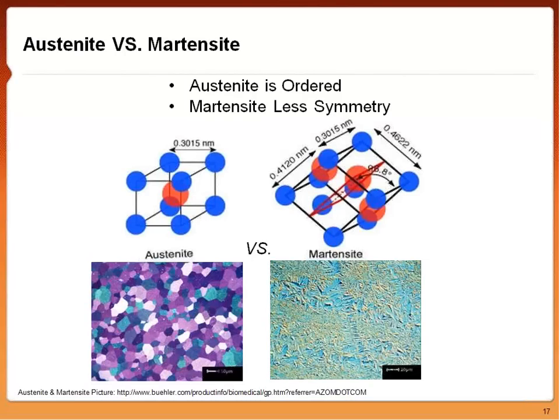Again, highlighting the differences between the two, austenite is more ordered, which produces a finer grain network. Martensite has less symmetry and produces the raised lenticular ledges for twinning. The key point is they're two distinctly different phases with two distinctly different sets of properties as well.